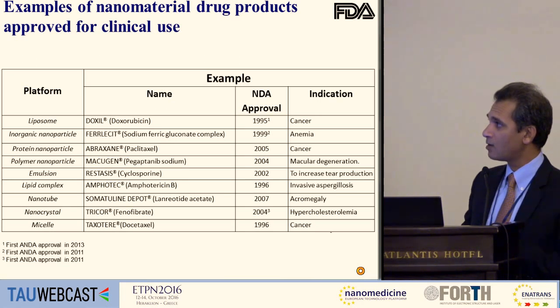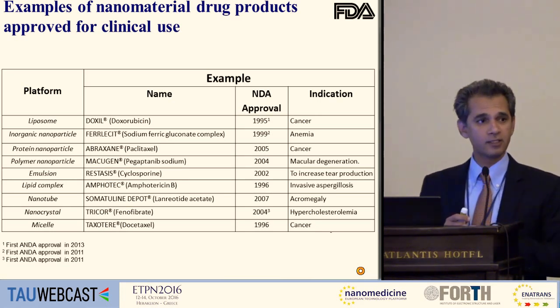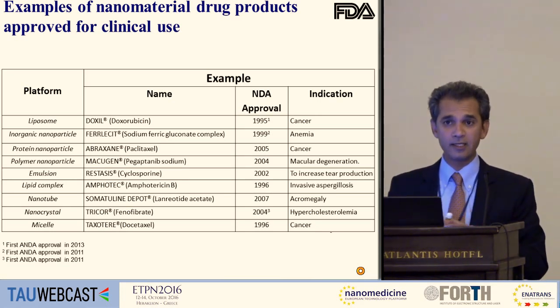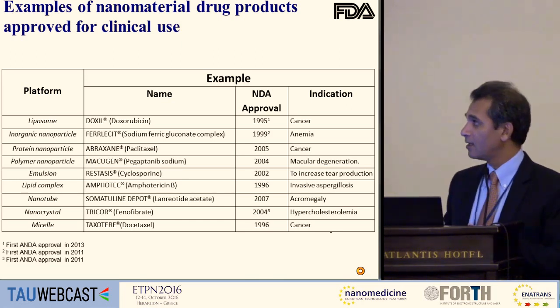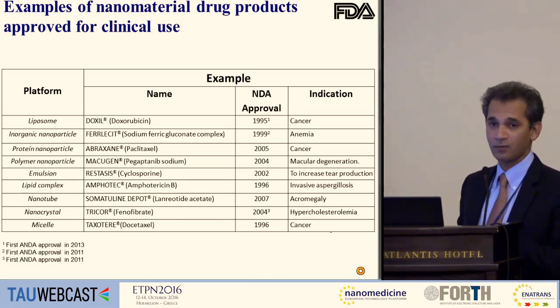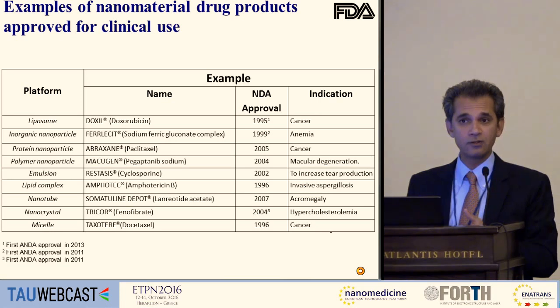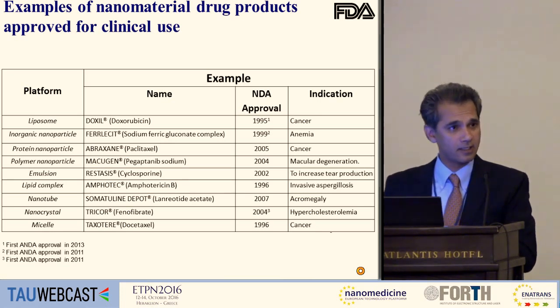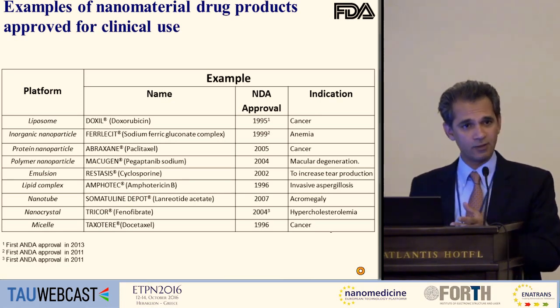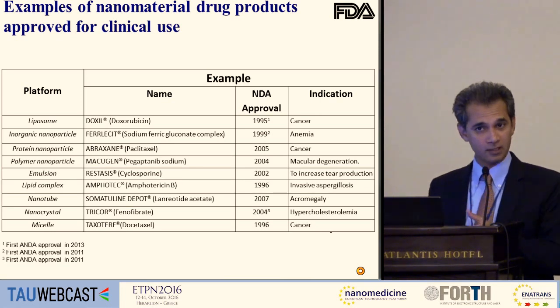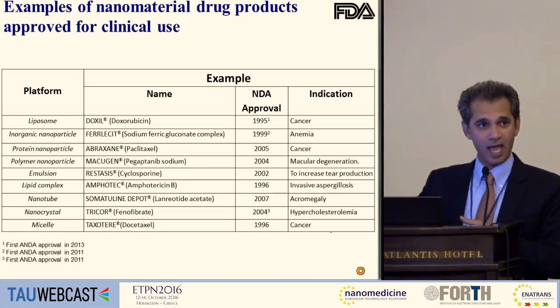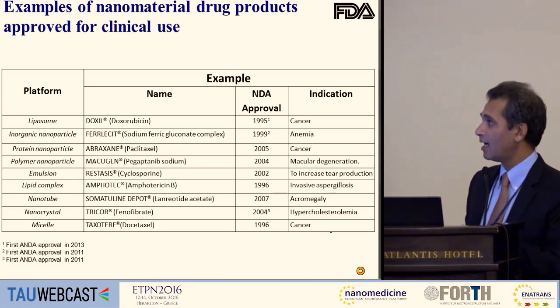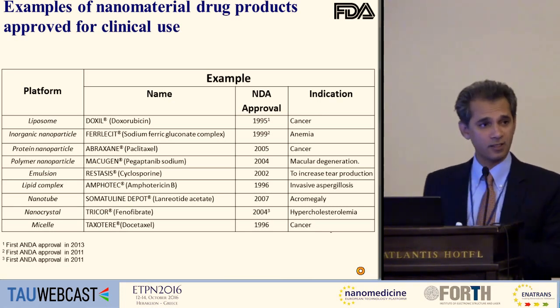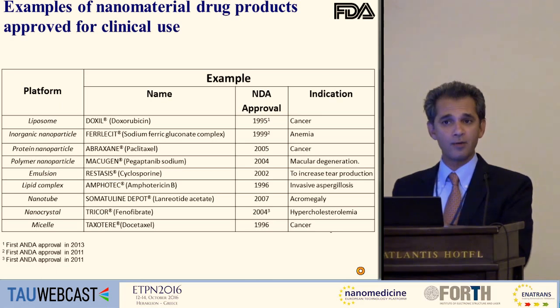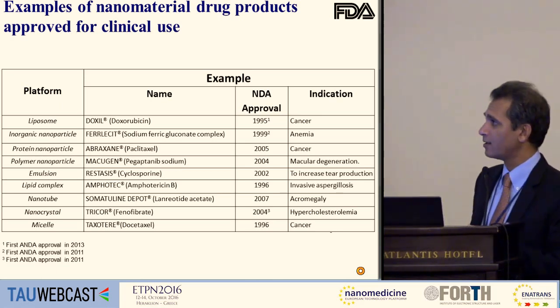Doxil, you probably know, is a doxorubicin encapsulated liposome. It's a pegylated liposome. The advantage of Doxil compared to the conventional doxorubicin, which is still used, is doxorubicin is cardiotoxic. But when you encapsulate into a liposome, you get away from cardiotoxicity. You prolong the half-life of the drug. And this is approved in 1995, more than 20 years ago. And now you have generic forms of Doxil that are in the market.